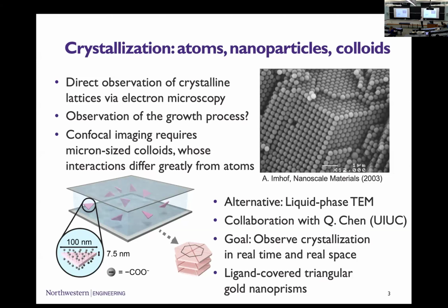It attenuates very quickly. Natural inclination might be to crank up the intensity of the electron beam. This is a really bad idea because you're going to ionize water like crazy. And so then everything changes. So instead, now people make these very thin cells. Let's say maybe few microns in width, I would say. So then the electron beam goes through a very thin slice of water, doesn't get attenuated too badly.